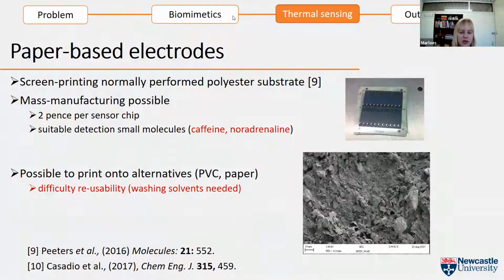But what we've then shown is that we don't need to print on plastic. We can go to paper-based electrodes. So the polymers that we have, we mix them in with the carbon black, which is the ink for the screen printing. We can use paper-based electrodes, and there's potential to regenerate these surfaces. So if you wash with a very mild solvent, even with soap, potentially you would be able to go to a reusable system, which is something that you normally don't want to think about. But if you could wash with, not an organic solution, but something as simple as soap, then that would obviously lead to less use of these plastic sandwiches.